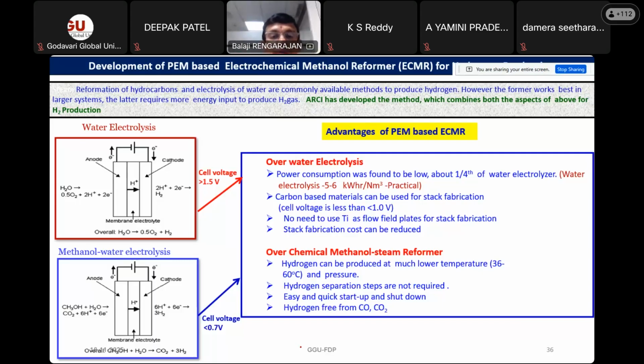If you use this 1 kg of hydrogen in the fuel cell, which is one of the best energy conversion devices in the world to convert hydrogen into power, even then the maximum power you can get from the fuel cell using 1 kg hydrogen is close to 15 to 17 units of electricity. So the input energy is about 50 units of electricity. Even if you adopt the best energy conversion engine, the fuel cell, you can hardly get 15 to 17 units of electricity. So there is a gap. Because of that, the overall efficiency is close to 30 to 35%, because 50 is the input and 15 is the output.